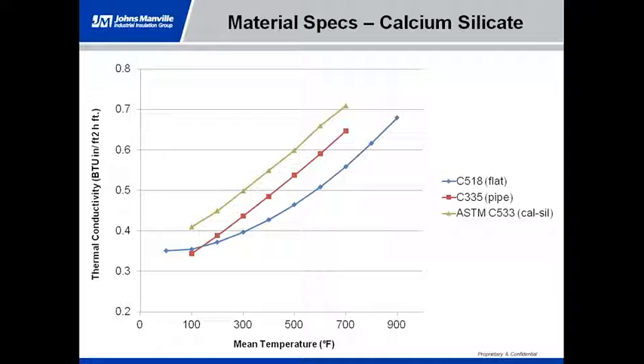The advantage here is that if I have a product that complies with the ASTM standard specification, in this case C533, that means the materials that I show the data here for will meet that specification every time, and we're considerably lower here. In fact, if you look at the data point at 200 degrees, we're a little less than 0.4, and the ASTM requirement looks to be 0.45, so it gives a considerable amount of leeway there.